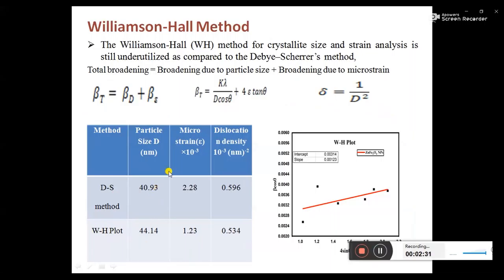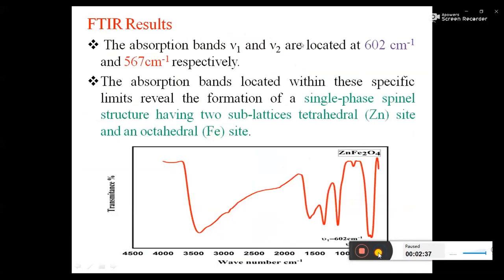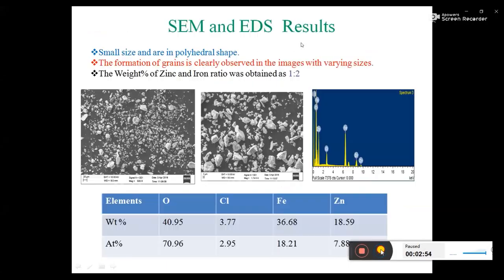And also we calculated the microstrain and dislocation density of the synthesized zinc ferrite nanoparticles. The FTIR results: the absorption bands ν1 and ν2 are located at 602 and 567 per centimeter. The absorption bands located within this specific region reveal the formation of a single-phase structure having two sublattices, tetrahedral and octahedral sites. SEM and EDS results. SEM results clearly show the polyhedral shape of zinc ferrite nanoparticles, and formation of grains is clearly observed in the image with varying size.